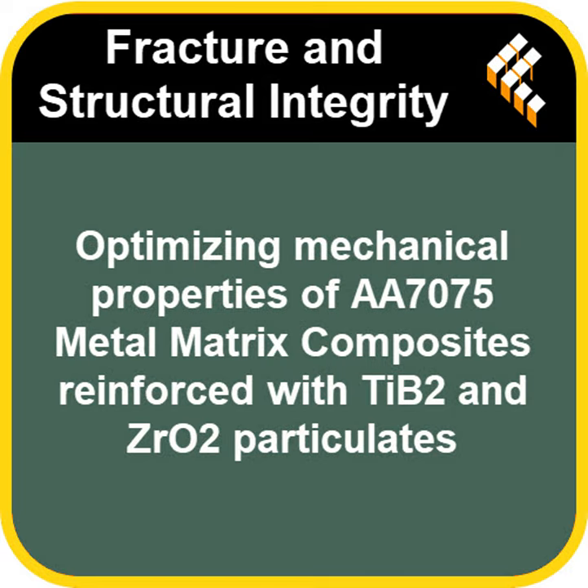Okay, TiB2. Got it. What was the second one? The second one was zirconium dioxide, ZrO2. You might actually know it as zirconia. From dental work, right? Crowns and things. That's the one. But industrially, it's also prized for high hardness, good strength, fracture toughness, meaning it resists cracking, and again, great wear resistance. It can handle temperatures up to about 2,400 degrees C. In fact, people sometimes call it ceramic steel. Its stiffness, what we call the modulus of elasticity, is actually pretty similar to steel's. Ceramic steel. I like that.